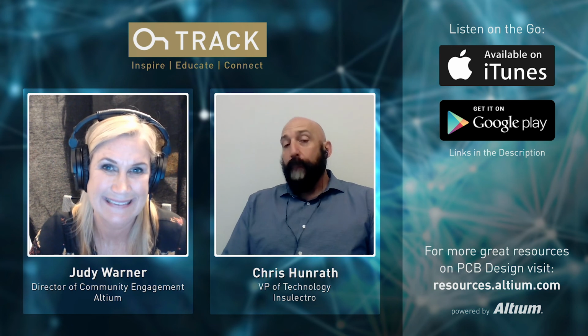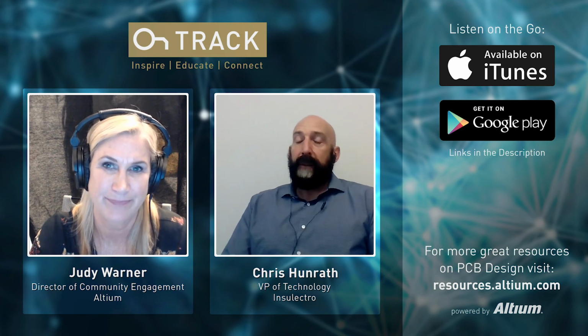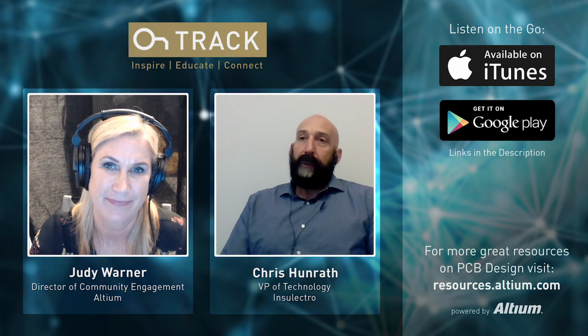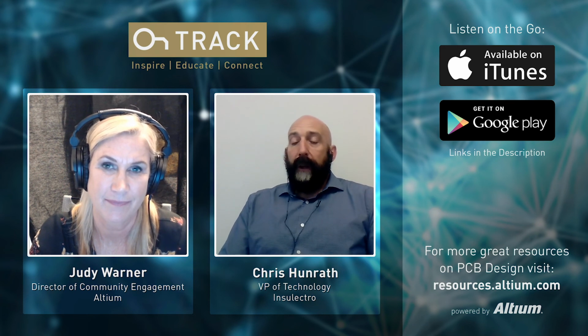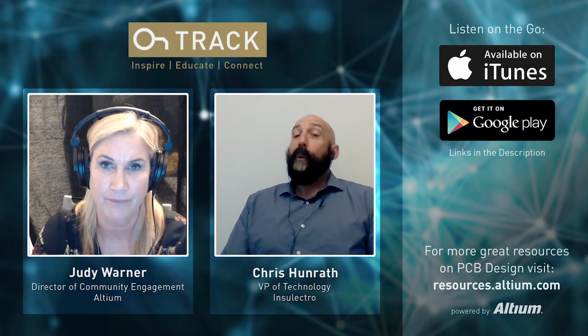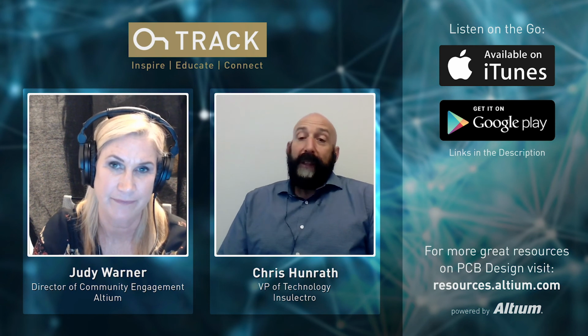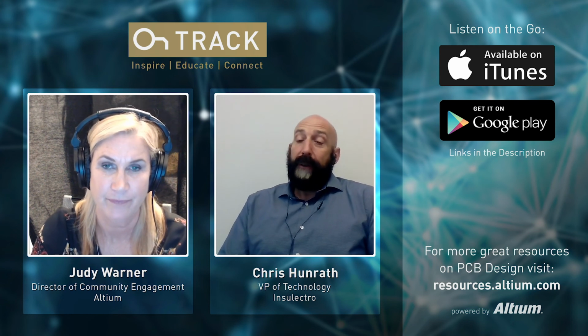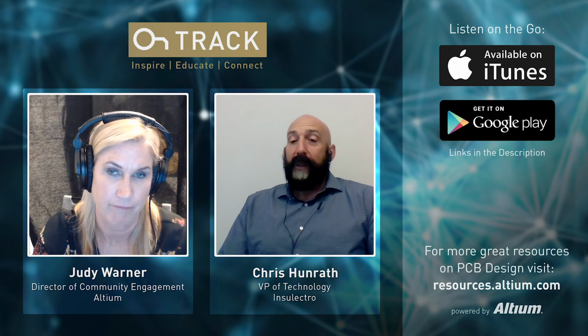It's kind of a shame, because if moisture is the only reason why you're delaminating at assembly, it really is avoidable. Yeah, sometimes it's a pain to bake a board for 2, 4, 6, sometimes 24 hours. But if that's what it takes to yield well, it's still worth it. And that's something that comes up a lot.